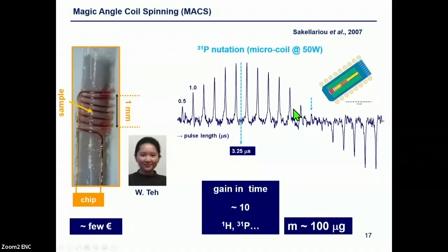How is it possible to characterize your microcoil from the RF point of view? You can simply record a nutation curve, which is here for phosphorus and for a given power. And from the 90-degree pulse, you can extract the efficiency of the coil, and you can even calculate an estimation of the gain in time, which is always at least 10 in the case of proton and phosphorus, for a few euros. So the entire equipment here costs a few euros. And I will show you in the next slides that it works for masses as low as 100 microgram.